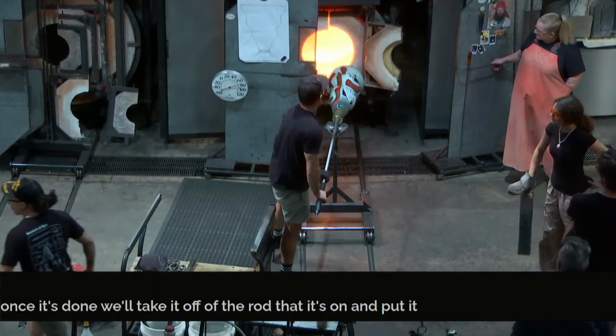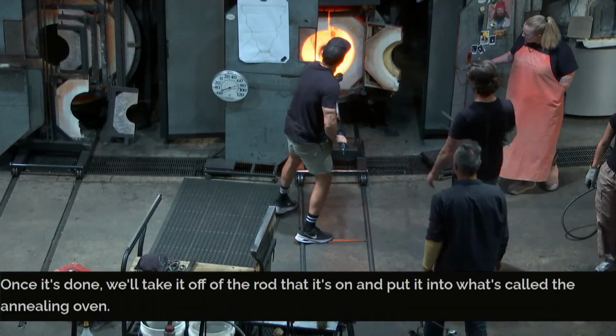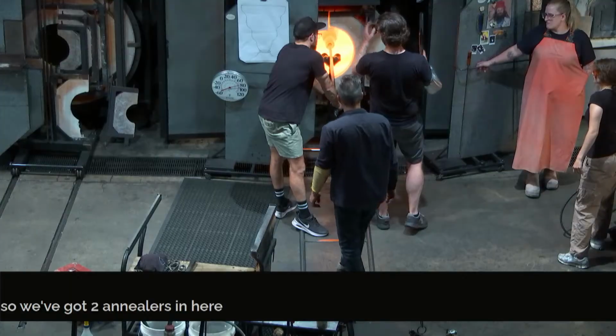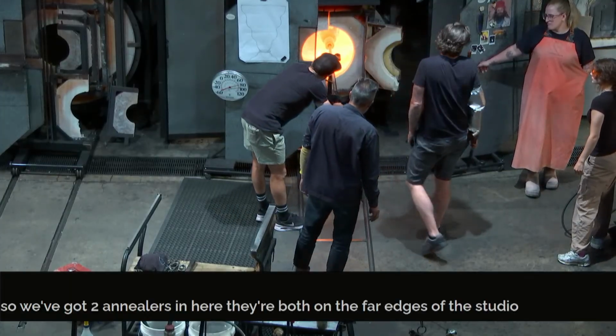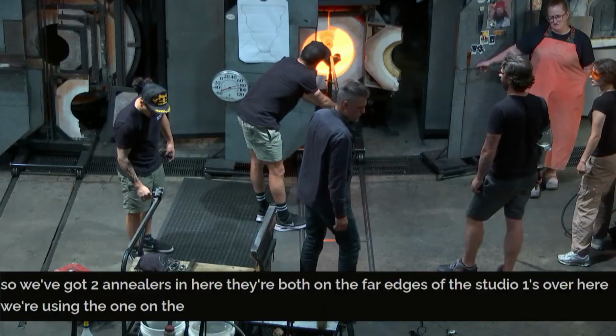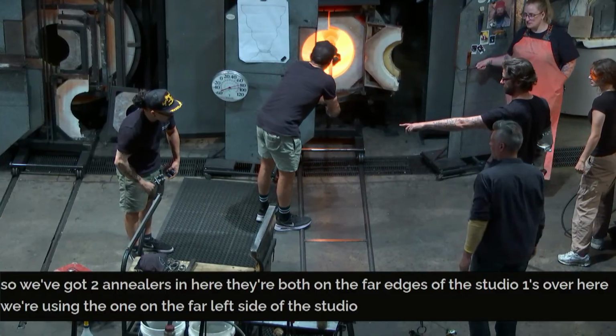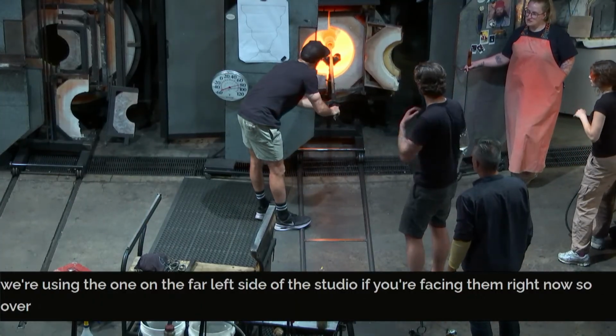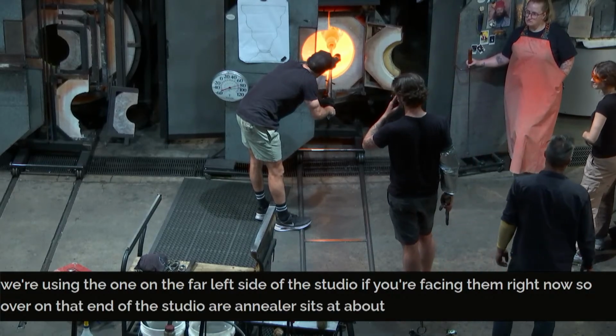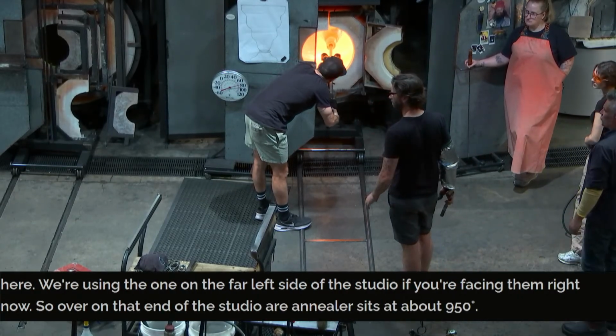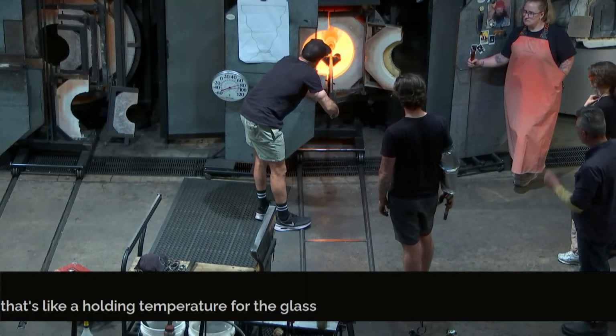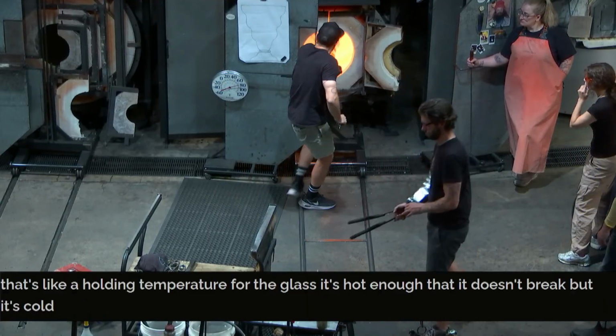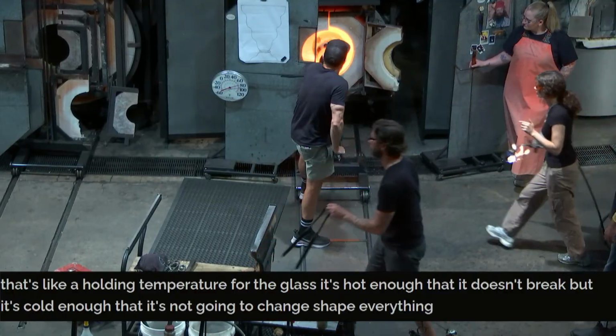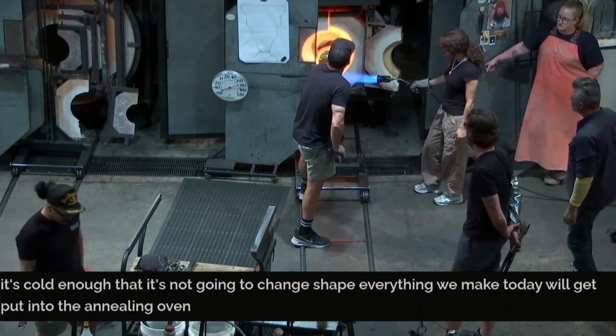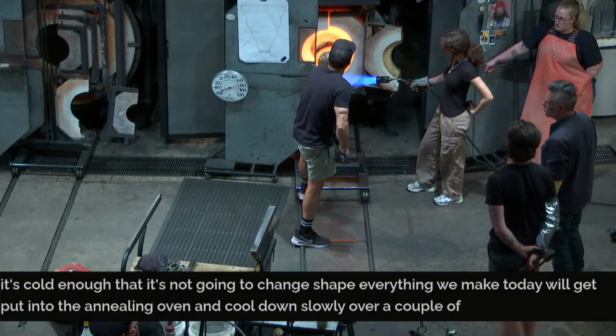Once it's done, we'll take it off of the rod that it's on and put it into what's called the annealing oven. So we've got two annealers in here. They're both on the far edges of the studio. One's over here. We're using the one on the far left side of the studio if you're facing them right now. So over on that end of the studio, our annealer sits at about 950 degrees. That's like a holding temperature for the glass. It's hot enough that it doesn't break, but it's cold enough that it's not going to change shape. Everything we make today will get put into the annealing oven and cool down slowly over a couple of days.